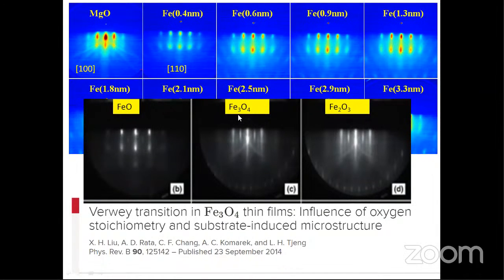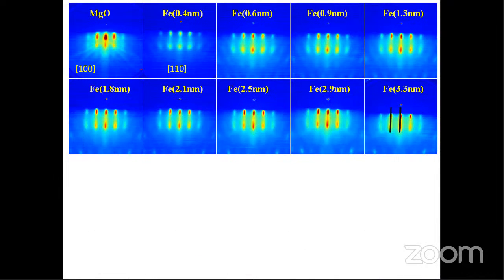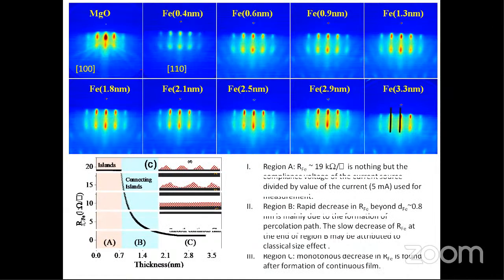And in the case of Fe3O4 formation, there should be an extra streaky pattern observed, and the same for Fe2O3. But in our case, during growth of Fe, no spot or streaky pattern has been observed. So we can say that there is no formation of any oxide at the interface during growth of the Fe film. This is the transport during growth of the Fe film.